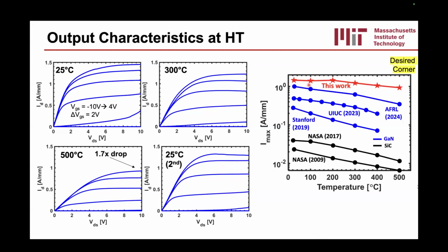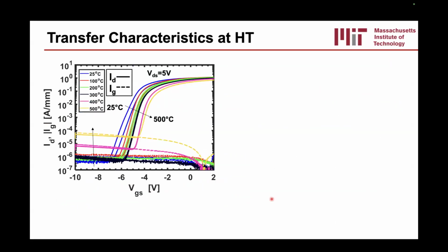And we can actually benchmark these devices. We can look at the maximum current density as a function of temperature for all wide bandgap semiconductor devices in the literature for GaN and silicon carbide. And we can see that because we have a very scaled device, we can get very high current densities compared to other GaN devices in the literature that have gate lengths of several microns, and especially over silicon carbide devices in the literature, which currently are about 100x lower current densities than what we are able to achieve. So we can see that indeed device scaling really does improve high temperature performance.